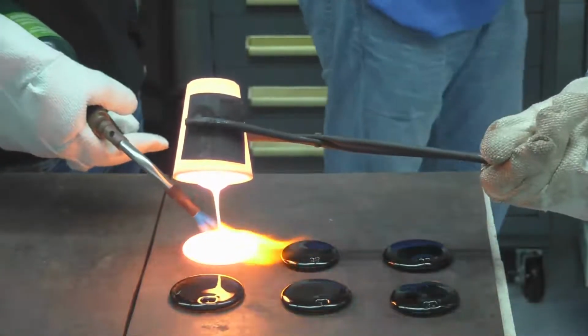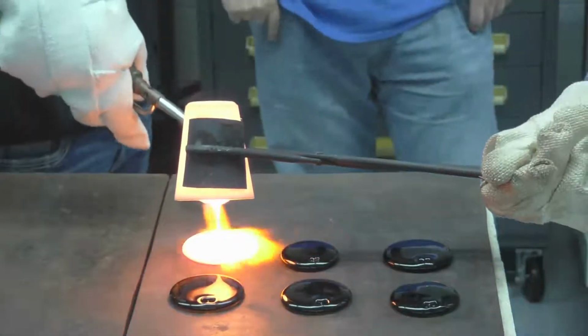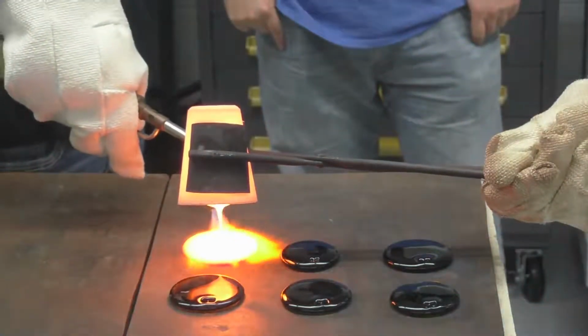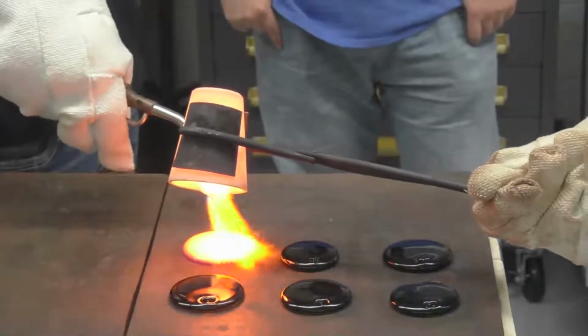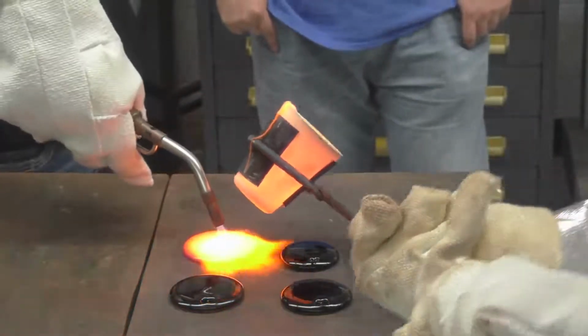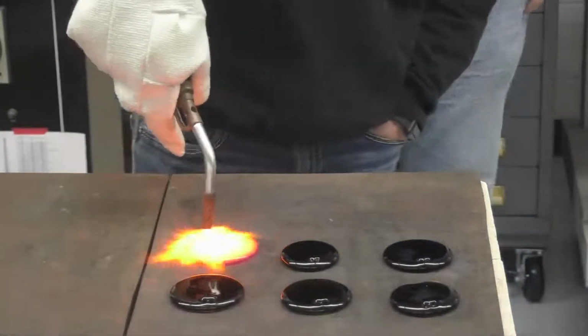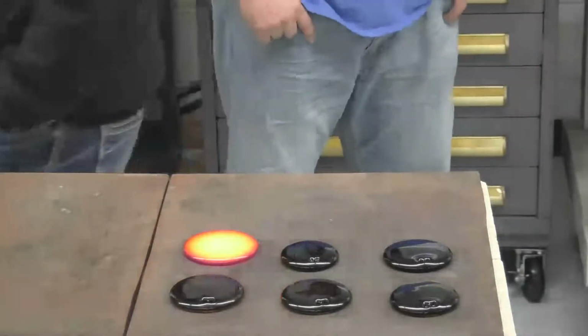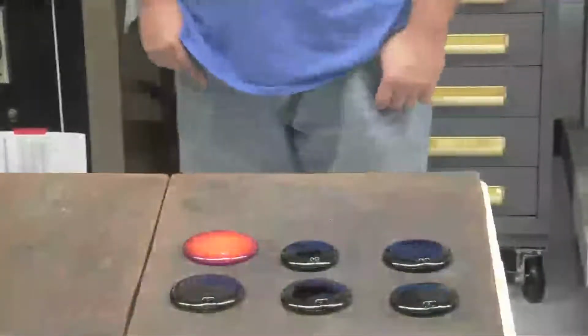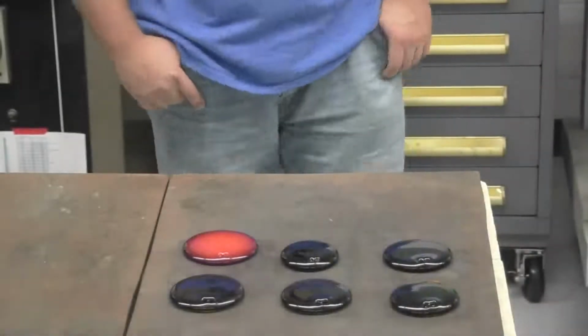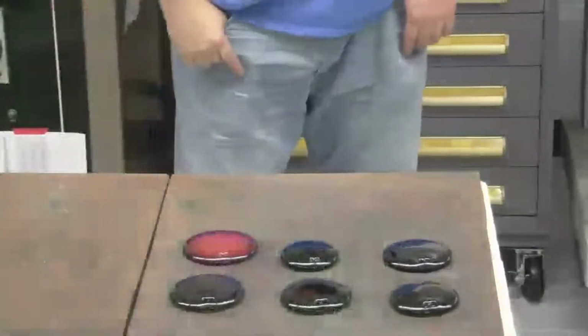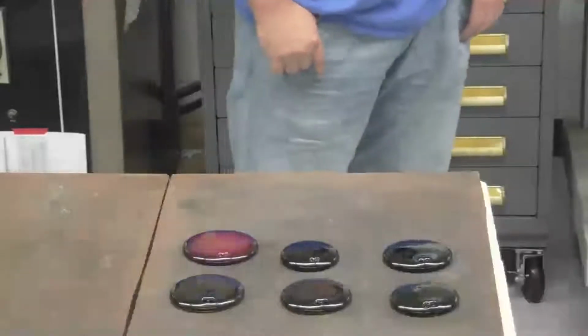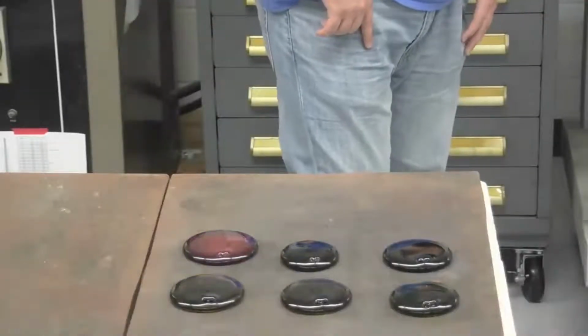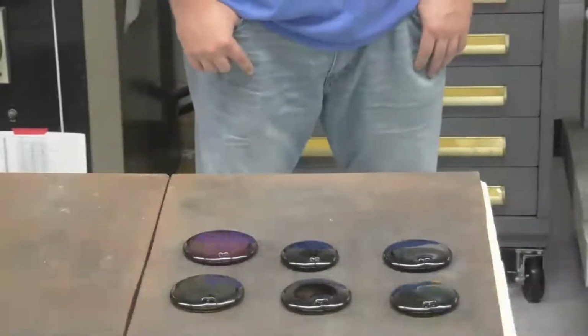That's pouring really easy. That's because of the extra high flux load. See how that just came shooting out? So low viscosity glass. Of course, viscosity always scales with temperature. So you could take a high viscosity glass at 1150, heat it up to 1300 and make a low viscosity glass. But we're comparing all these at a standard pouring temperature of around 1150 and then benchmarking viscosity. But you can always take a higher or lower pour temperature and get whatever viscosity you want.